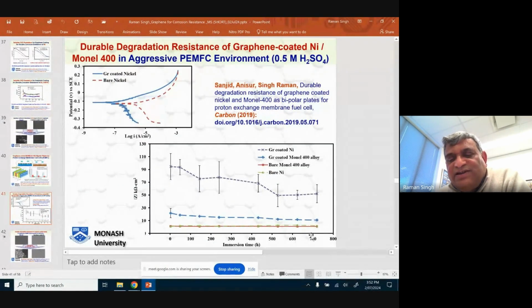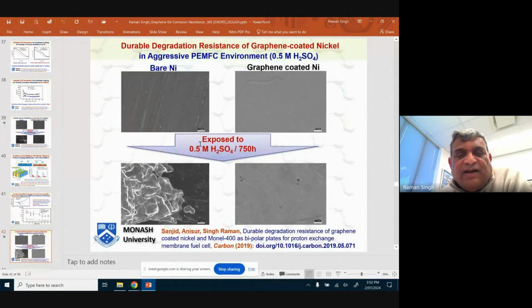Corrosion data, as you can see, more than 700 hours in a highly corrosive sulfuric acid environment. And again, this work was published in Carbon. In the post-corrosion characterization, you can see the sample before the corrosion test. After the corrosion test, you have only a few spots here and there. Otherwise, it is corrosion-free. Whereas bare nickel in this condition will be finished. A 2 millimeter thick sample will be finished in no time.